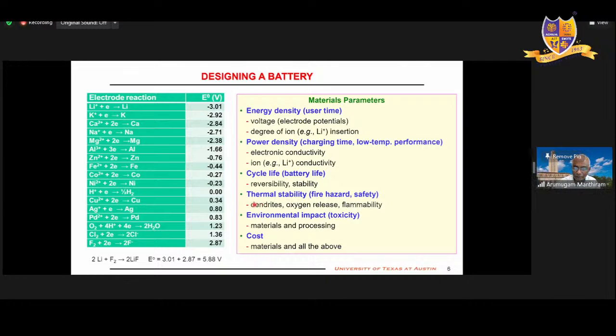As soon as it goes up, the cathode, cobalt oxide, says okay, I will release oxygen, because cobalt 4+ is not very stable. Nickel 4+ is not very stable. Oxygen comes, the liquid electrolyte is there, the organic electrolyte, that is like gasoline. Okay, we caught fire, I will help you. That's what is happening. All three of them mess around.